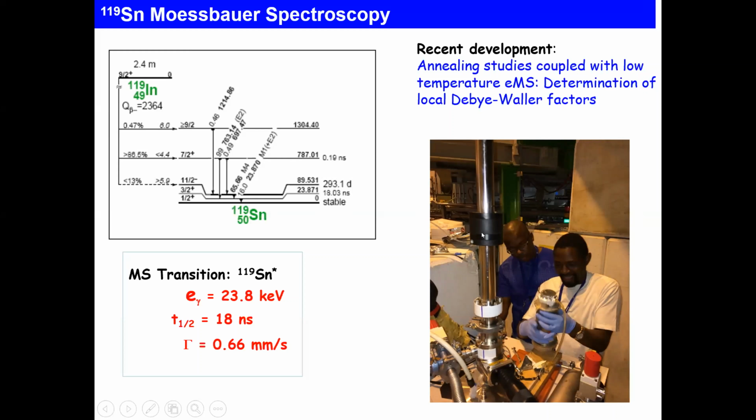This has a drive that allows one to extract the sample, immediately shut off the area so the sample is on vacuum, and then it could be taken and immersed into a liquid nitrogen bath to allow Mössbauer measurement at liquid nitrogen temperature. Some examples of that I'll show in a short while.